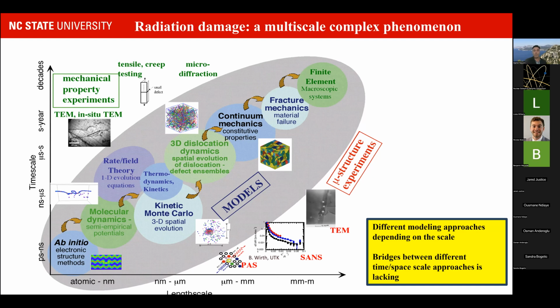Radiation. To give you an idea of where those experiments sit in the realm of radiation damage, which is a multi-scale complex phenomenon, as you know, I use this schematic that a lot of you have probably already seen. It's borrowed from Brian Wirth. It shows how radiation damage is a multi-scale phenomenon, with processes that happen at the atomic level and at the picosecond scale or even less, but that can have effects at the macroscopic level, the millimeter to meter range, many months or years later after accumulation of damage. And depending on which aspect of radiation effects you are looking at, you're going to have to use a specific modeling approach and a specific experimental approach to benchmark the model.